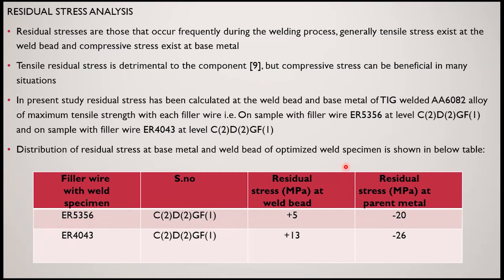Various researchers have suggested that tensile residual stress exists at the weld bead and compressive residual stress exists at the parent metal. Basically, here plus indicates tensile residual stress and minus indicates compressive residual stress. Our results also match the suggestions of researchers: we are getting tensile residual stresses at the weld bead and compressive residual stresses at the parent metal.